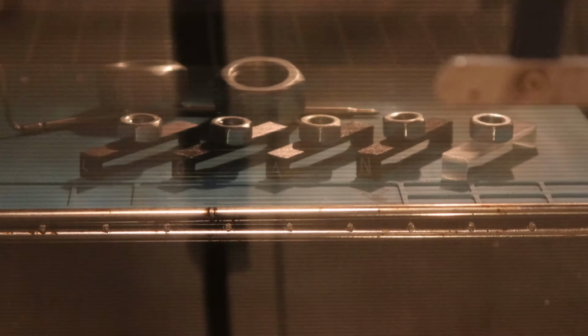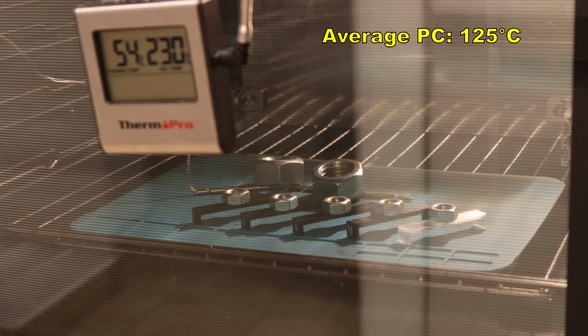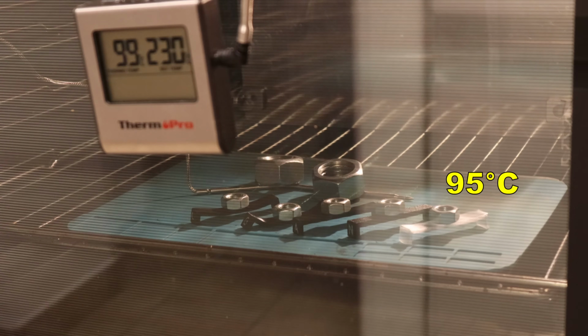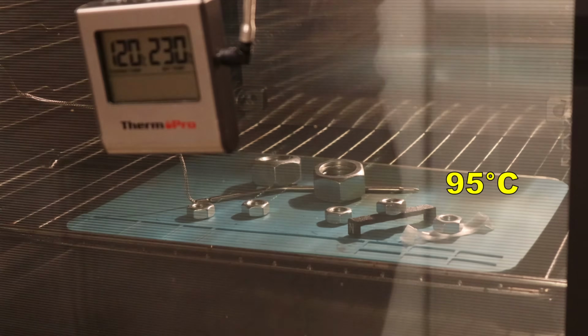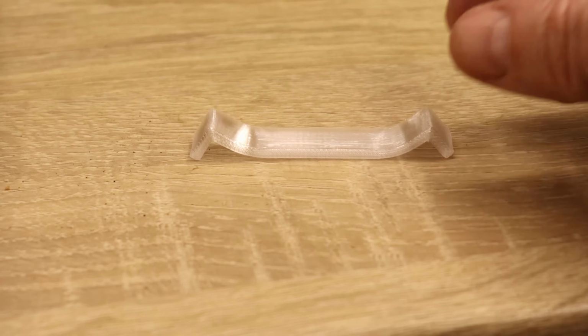I want to record the temperature of the first deformation. And the average value for the polycarbonate is 125 degrees Celsius, but this Durabio is closer to the carbon fiber ABS in this case, and started to deform at 95 degrees Celsius.